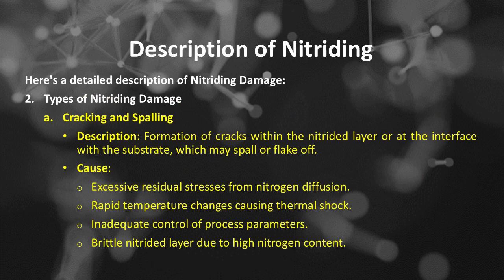Number 2 is types of nitriding damage, which includes: A, cracking and spalling, described as formation of cracks within the nitride layer or at the interface with the substrate, which may spall or flake off. Causes of cracking and spalling include excessive residual stresses from nitrogen diffusion, rapid temperature changes causing thermal shock, inadequate control of process parameters, and a brittle nitride layer due to high nitrogen content.